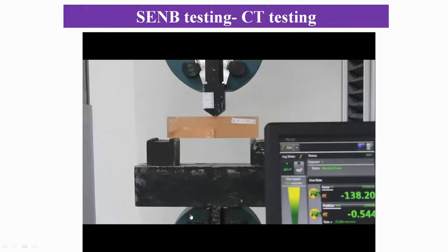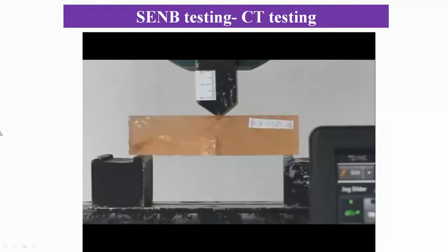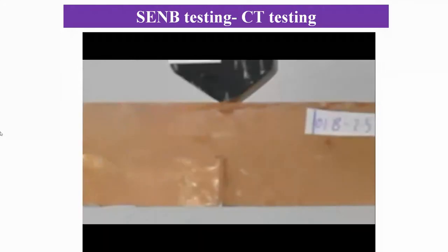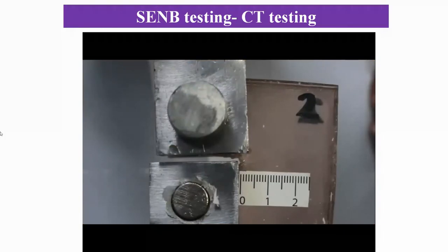This video shows the process of single edge notch bending testing. As you see, a fast fracture happens during this test. And this is compact tension testing. We have added a label to observe the crack propagation. And again, you see a fast crack propagation and fracture.